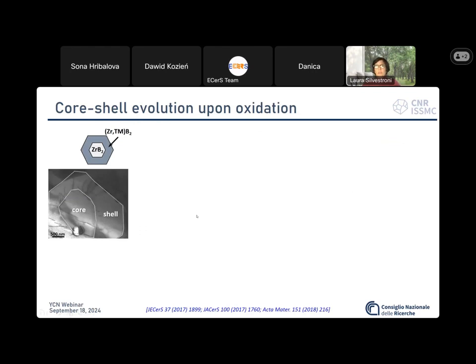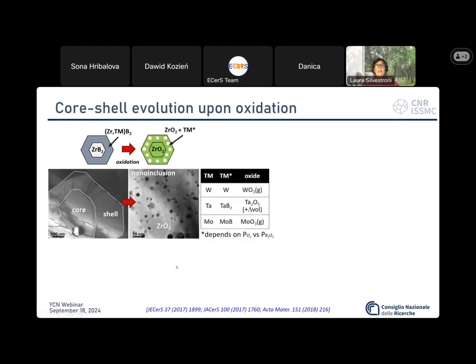So zirconium diboride is the compound that most favorably oxidizes, and its oxidation protects the particles which remain nestled inside. Then, depending on the system, the particle evolves as boride or remains as metal. And in turn, we might have problems or not if the oxidized phase at the testing temperature is solid and might have some volume expansion, or liquid, and in that case could fill the voids, or it's vapor, and in this case would create bubbles and leave the system.